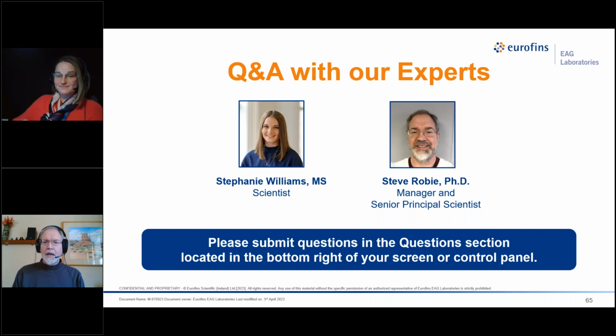Steve? I think I'd add that whether a quantum dot is a single crystallite or not is important. SAXS will tell you the size of the particle, but the actual domains that are doing the diffracting might be smaller than that, and you can tell that through the Scherrer equation in the crystallite size. Quantum dots typically have very small crystallites, maybe a couple of nanometers, so you have a very broad diffraction pattern instead of these nice sharp ones that we've been showing.